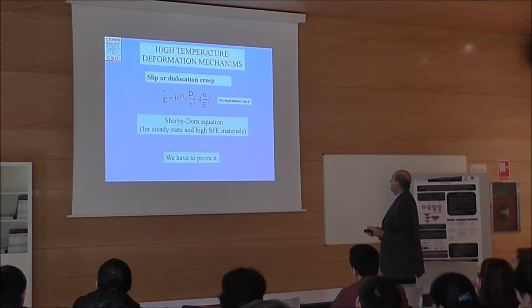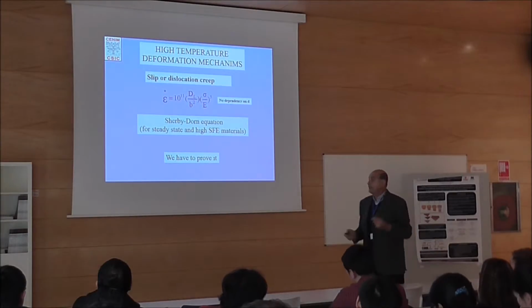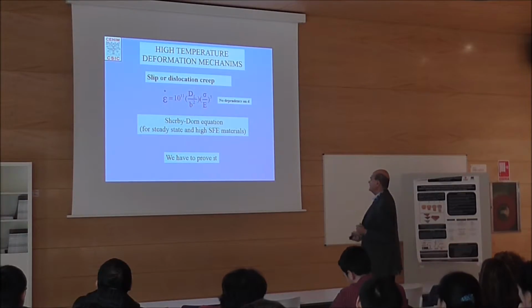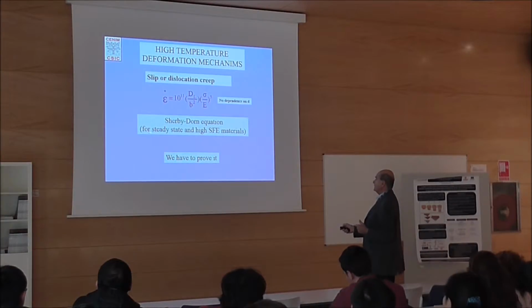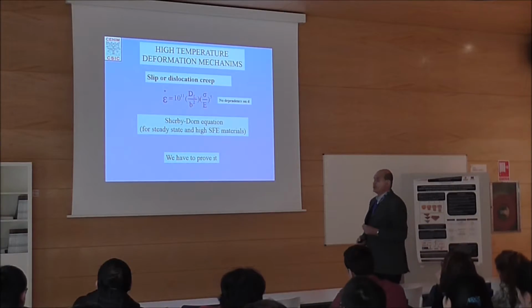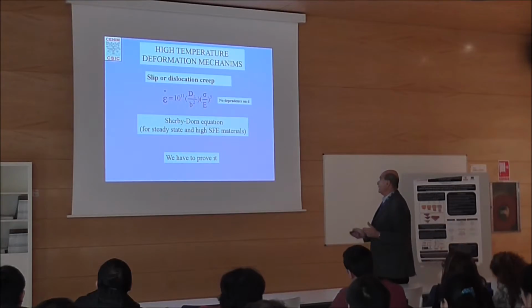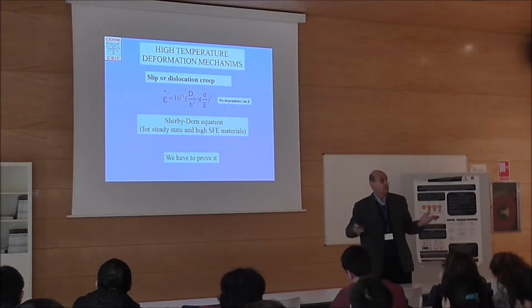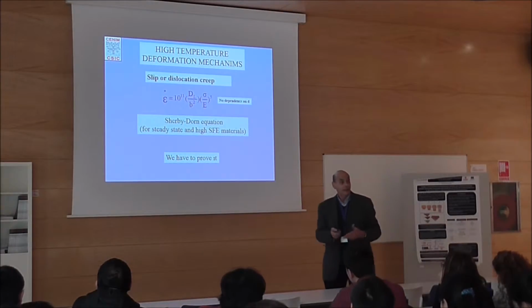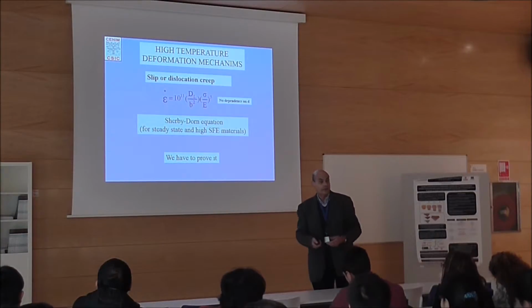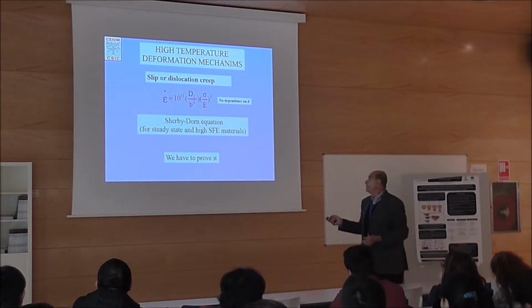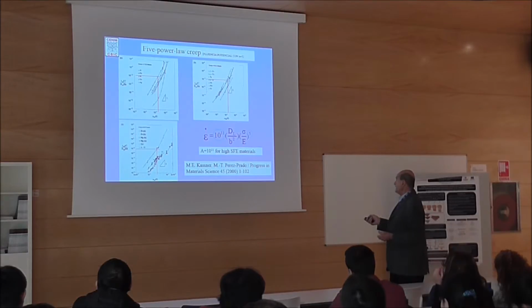Here you see the first thing is no dependence on grain size. And this is a very well-known Sherby-Dorn equation. This is for steady state and high stacking fault energy material. And now we have to prove it. Okay, you say that, it's fine. We can use it to correlate our data, but is this true? And the answer is, yes, it is true.